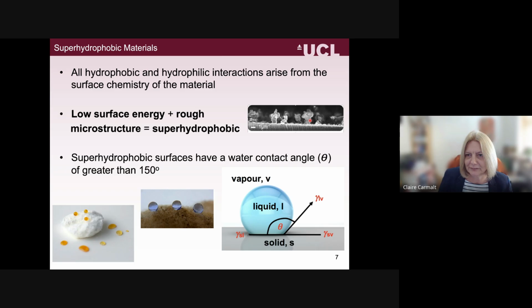But they also need to have a very low surface energy. And that's because when you put water onto the super hydrophobic surface, rather than the water spreading out, it actually forms, due to the high water repellence, these spherical water droplets. And because of the low surface energy as well, they don't stick to the surface, and so as they roll they can act as sort of self-cleaning or help to clean. Now, to define if something's a super hydrophobic surface, we measure the water contact angle, and it's showing you here how we measure what the water contact angle is. And if it's hydrophobic, it's above 90 degrees, and if it's super hydrophobic, it's above 150 degrees.